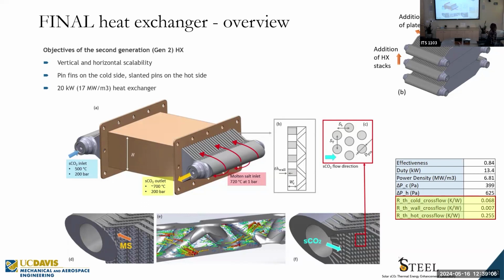So in order to improve this aspect, we added these fins that are basically slanted so that we can increase the surface area, but also promote more mixing so that the fluid has to turn some more before it exits the unit, and it has more residence time within the heat exchanger to transfer heat. Yeah, and another interesting aspect of this heat exchanger, it's a little bit obstructed, is that we can scale it horizontally by adding more plates, but also vertically by stacking more units one on top of the other.